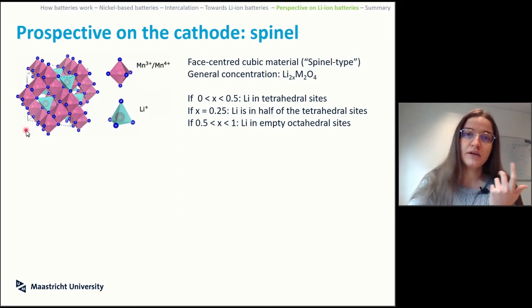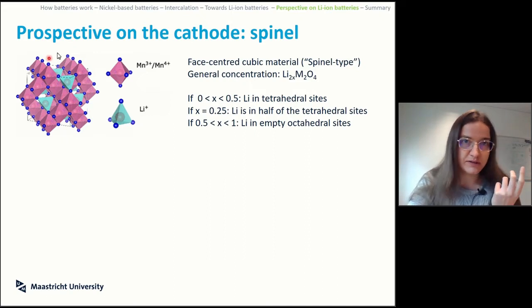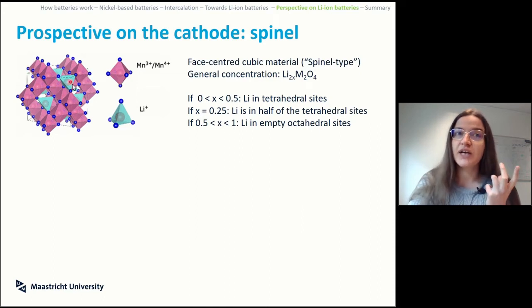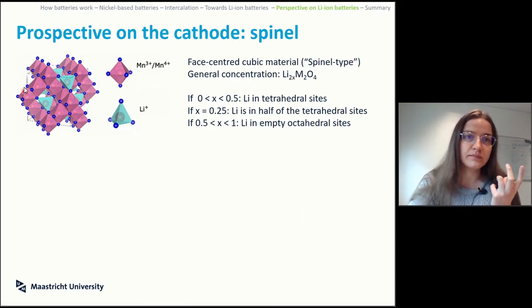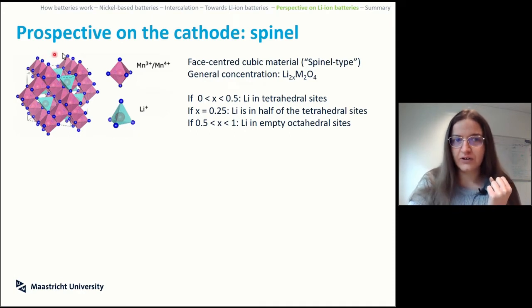One thing that you can do is use the spinel structure. As you can see, the spinel structure is a completely different arrangement. You have this face centered cubic material with chains of corner sharing and edge sharing octahedra, chaining in 3 dimensions. And what is not an octahedron is a tetrahedron that is corner sharing with the octahedra. This can be done with manganese, for instance.